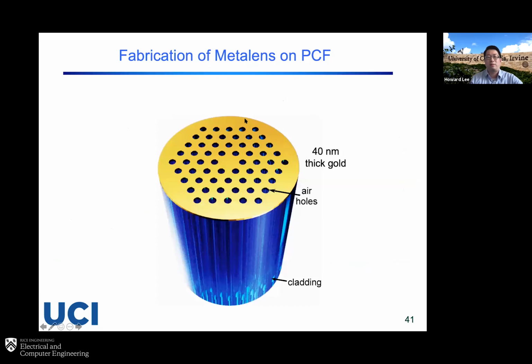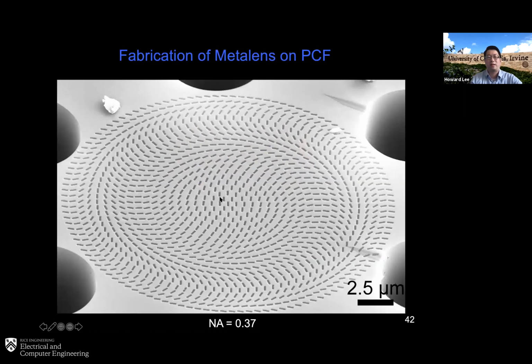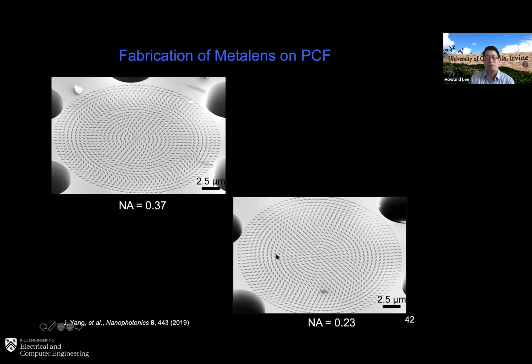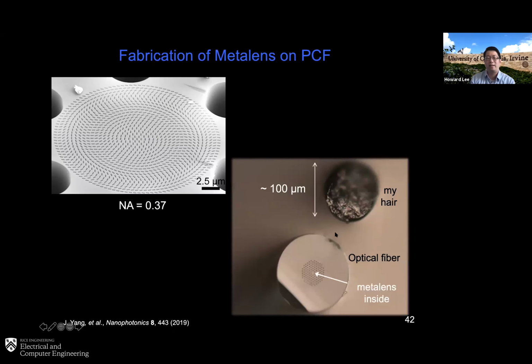To fabricate the structure, we coat a thin film of gold, 40 nanometer, and then use a focused ion beam to mill the structure. And this is the structure my student made. So you can see in the core of the fiber, we're making this tiny slit and rotating the geometry angle, so that you can have a rotating geometry to achieve the phase profile we need to make a lens. And this is for one lens, and we can actually make another lens with a different distribution here. And just to keep in mind again the dimension of the optical fiber, this is the fiber itself, and this is my hair, 100 micron, and the core is inside, and we're making the metasurface at the center of the core. So we're making a really tiny structure, more or less like on the end face of the hair.